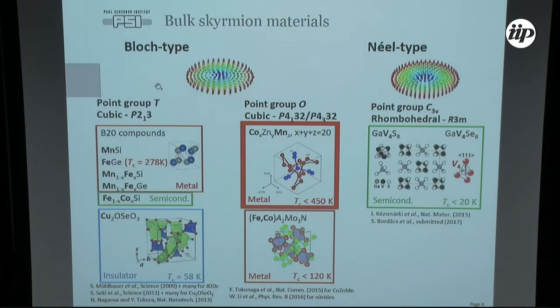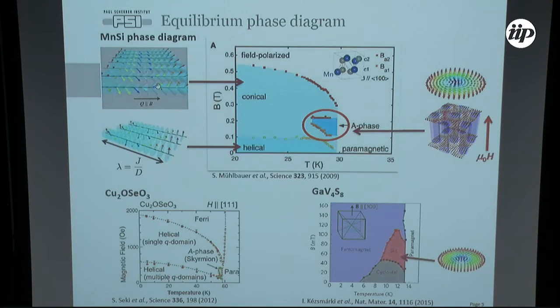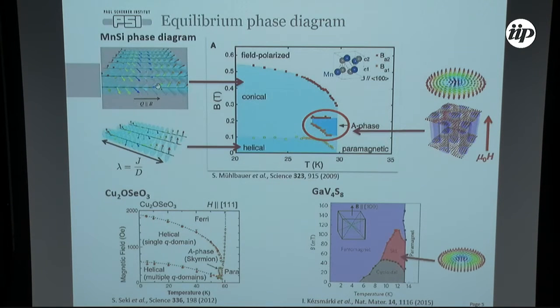The Néel-type skyrmion has been reported in spinels. Importantly, that material has a readily tunable composition and a much lower ordering temperature than any of the other materials, offering an exciting system to explore a broad parameter space for skyrmion physics. The equilibrium magnetic field versus temperature phase diagrams for skyrmion materials share the same structure despite their different internal structures. This phase diagram is characterized by a zero-field helical state, followed by a conical phase under finite field, and then the skyrmion A-phase, which is stabilized by a small magnetic field and exists only over a few Kelvin.